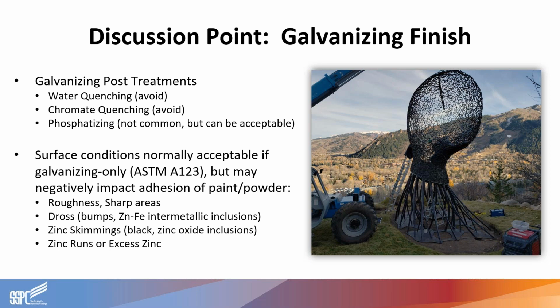I've listed some common examples here, such as roughness and sharp areas, the presence of dross inclusions, which are bumps that are really zinc and iron intermetallic alloy inclusions. There is the inclusion of surface or bath oxides that are black in color called zinc skimmings. There's also zinc runs or other areas of excess zinc. Those can be some common examples that you may want to specifically call out for addressing.